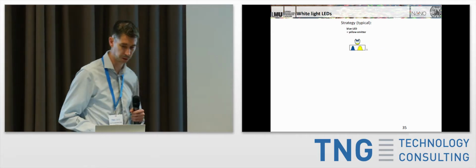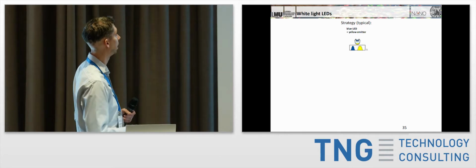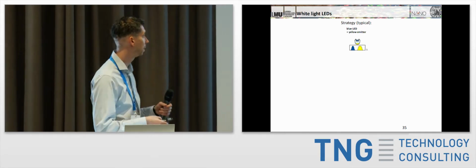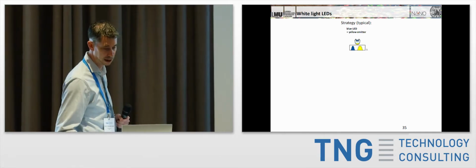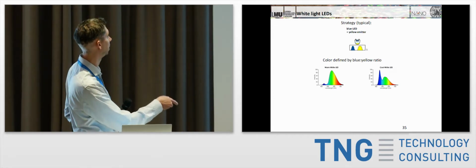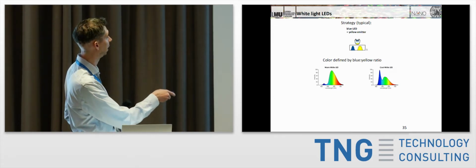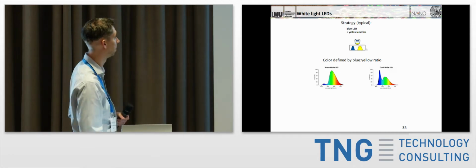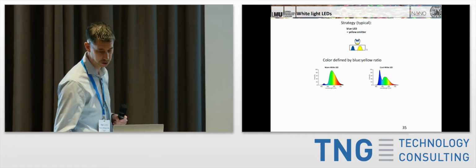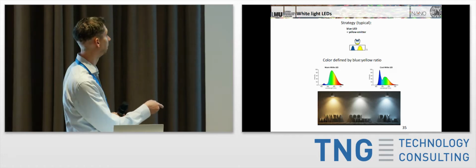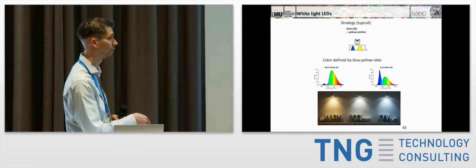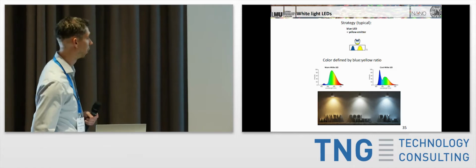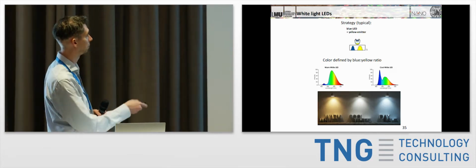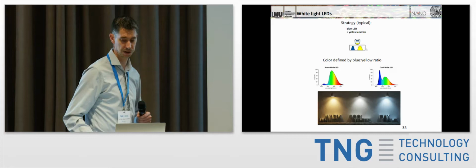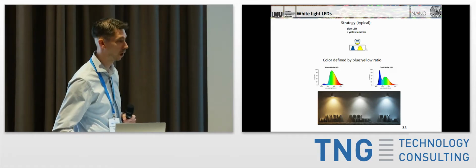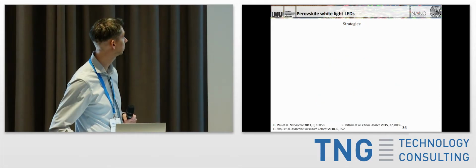But typically, how people get around this is they make a blue LED, so a nitride-based LED, and have a yellow absorber and emitter on top of that, which absorbs some of this blue light and emits it. Basically what you're doing is tuning the amount of blue light that's still coming through with the yellow light that's produced by this phosphor, and that gives the different color spectra that we can see there. That's what we're calling warm white and cool white or daylight, or all these different types of white scales. Essentially, all we're doing there is changing the blue to yellow ratio, and that changes the apparent light or the whiteness of the light that we're getting out.